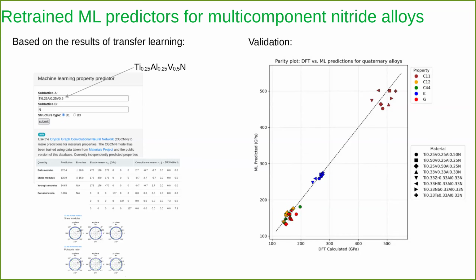We can come to the other point, where the built-in CGCNN neural network works for industry. This is the case where we are using a multi-component alloy, which is not at all in the database. At the moment we have binary and a couple of ternary alloys in the database. But if I type in titanium, aluminum, vanadium nitride with a certain concentration, it's not in the database. But the CGCNN models, based on the success of the transfer learning approach, can be used. And we did it. So that works very nicely.